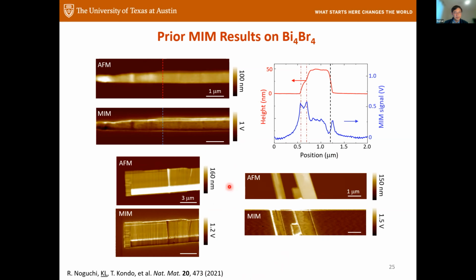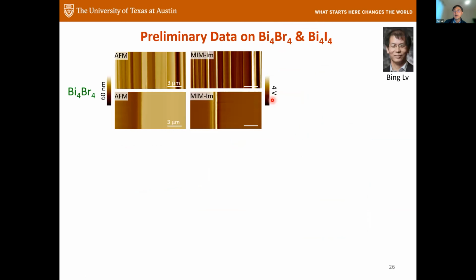And then after that, immediately the pandemic hits, and I sort of dropped the ball until Fan sort of convinced me. And also after I saw the nice result from Hossain's group showing that even at room temperature, you could expect things coming out from this material. So just this past Thanksgiving, very fortunately Fan connected my group with Bing's group at the UT Dallas. And this time we get samples much wider.